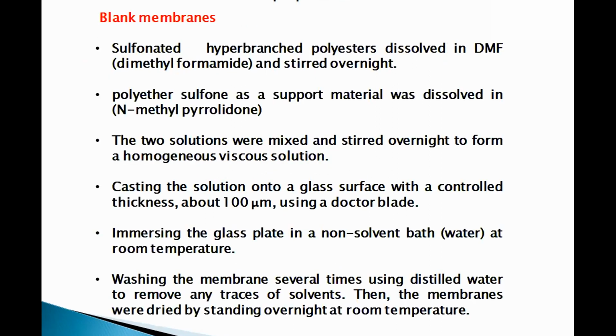Membrane preparation: we prepared two types of membrane, blank membrane and composite membrane. For the blank membrane, we prepared two solutions. The first one is sulfonated hyperbranched polyester dissolved in dimethylformamide and stirred overnight. The second solution is polyether sulfone as a support material dissolved in N-methylpyrrolidone. Then the two solutions were mixed and stirred overnight to form a homogeneous viscous solution.